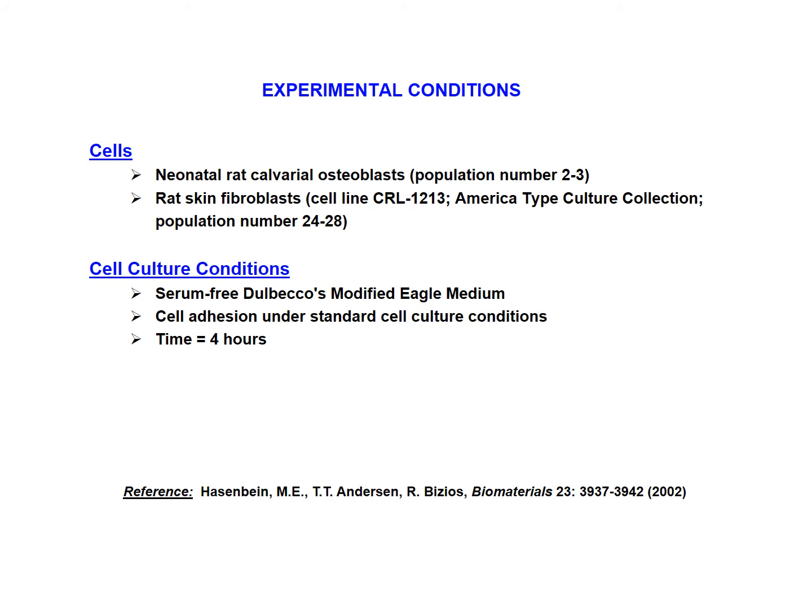The respective cells were allowed to adhere on the substrates for 4 hours, and then the results were visualized using fluorescent microscopy and in some cases light microscopy to visualize the patterns and the cells on the modified substrates at one and the same time.